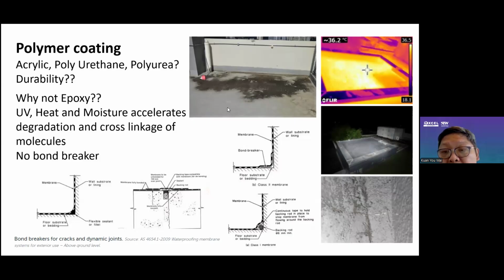And for your information, for coating or any other system, the problem is always the joints where the expansion and contraction will tend to work, in those joints at the edges as well as at the penetration to the pipe. So this area needs extra attention, whereby we do need to install a bond breaker to prevent the waterproofing from breaking at this location. Okay, but unfortunately, I have hardly seen this in the industry.